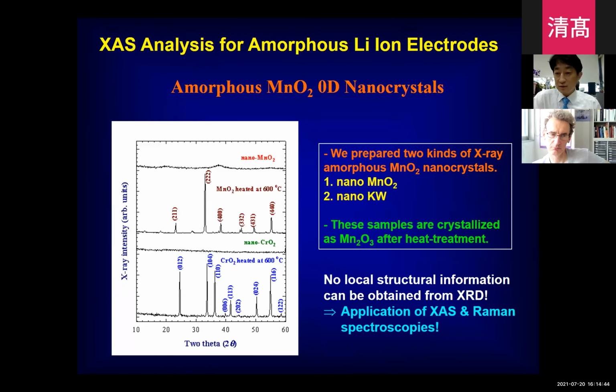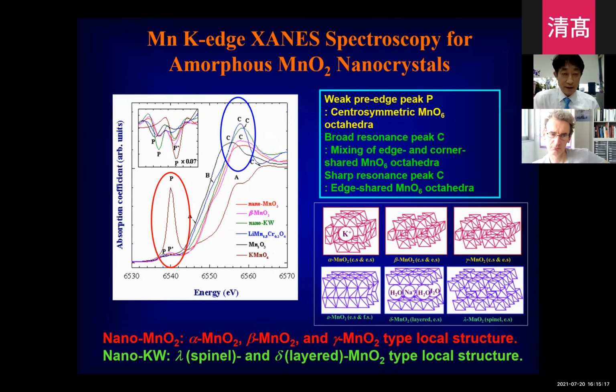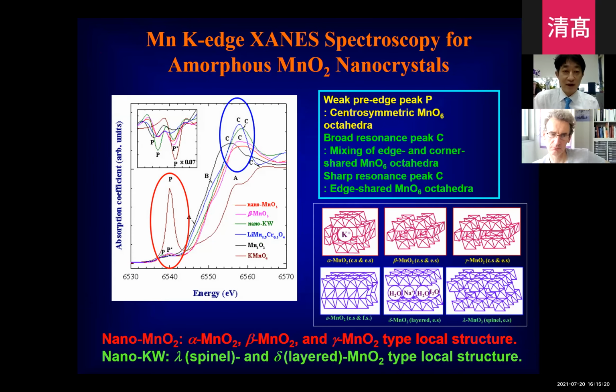A long time ago, we synthesized amorphous manganese oxide nanocrystals as a lithium-ion electrode. We synthesized two kinds of amorphous manganese oxide nanocrystals. We named them nano MnO2 and nano KW. We confirmed the amorphous nature of those materials, so from the XRD we cannot get any structural information about these materials. So we applied X-ray absorption spectroscopy and Raman spectroscopy. So this is the Mn K-edge XAS spectrum.